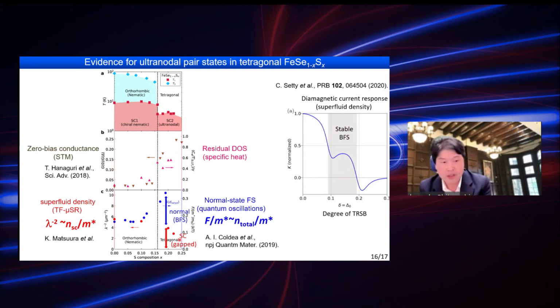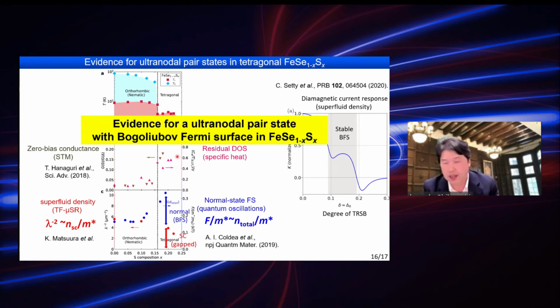So from this set of data, we have concluded that we have obtained experimental evidence for an ultranodal pair state with Bogoliubov Fermi surface in the tetragonal side of iron selenium sulfur. So this is our conclusion.